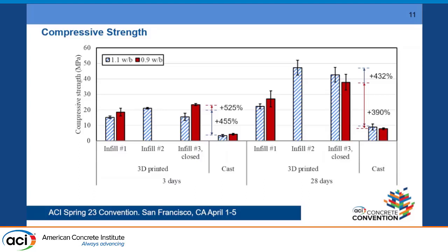Now, what was interesting to me is that typically with cement, as we increase the water to binder ratio, we would end up losing strength. And what I was finding here, which was strange to me, opposite to the early age, was that my mixes with the higher water to binder ratio were the ones with the higher strength. The second interesting part is that the samples with closed infill, so no internally hollow structures, were also keeping a similar strength to the open internal structure. And I expected them to be something similar to my cast specimens.